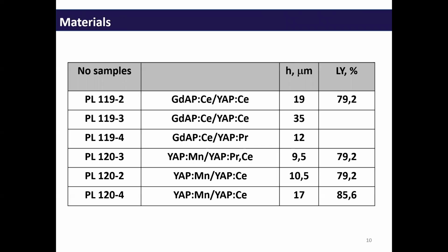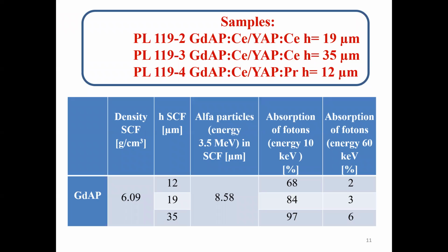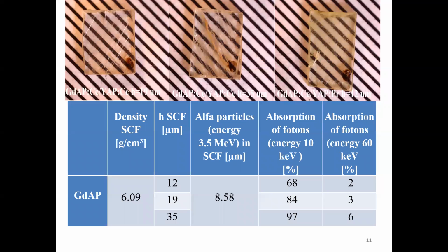The choice of the mentioned dopants in these materials is due to the fact that these ions typically create the hole cerium-3+ and electron manganese-3+ trapping centers in oxide compounds. For this reason, the TL glow curves in the mentioned materials can a priori be significantly different. The first sample is gadolinium aluminium perovskite. We see in this table alpha particle absorption with energy 3.5 mega electron volts, and absorption of photons with energy 10 kilo electron volts and 60 kilo electron volts.